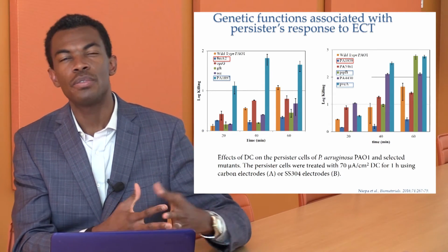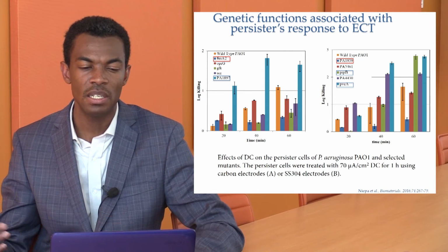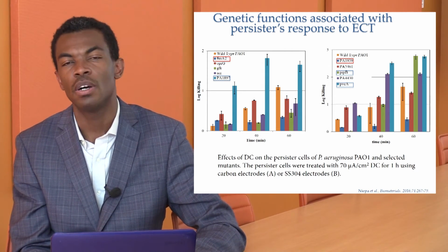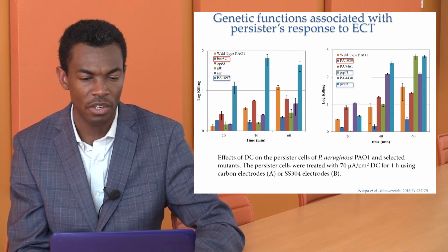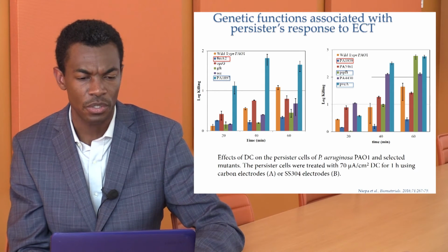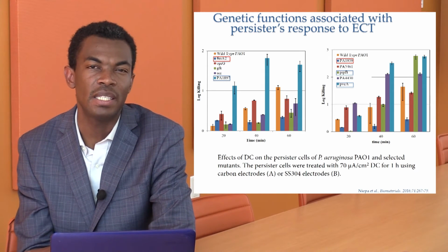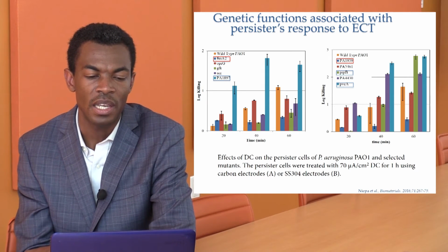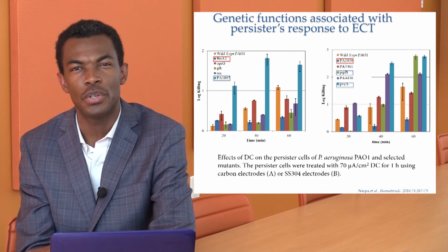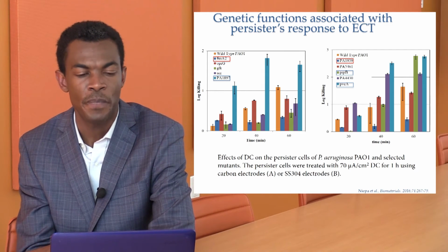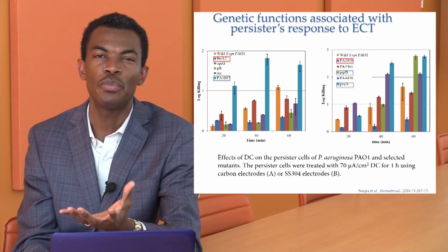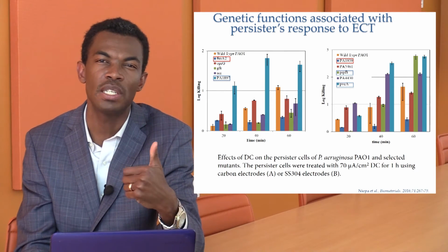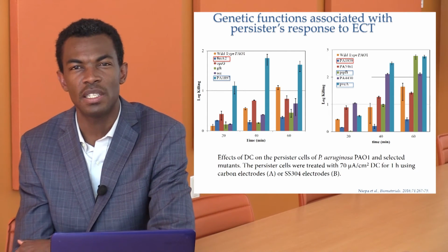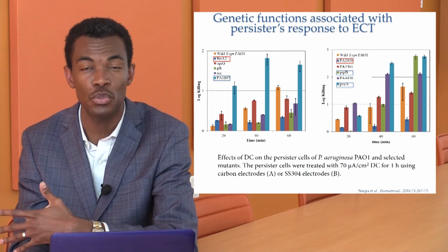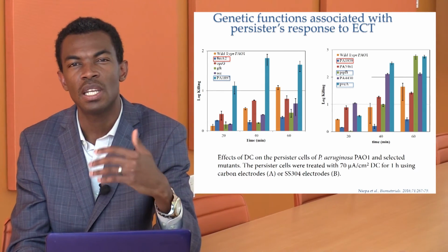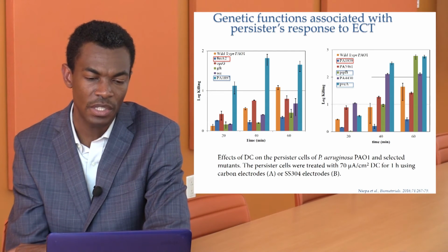Focusing on the genes that are involved in the treatment with carbon electrode versus the treatment with stainless steel, we performed the DC treatment to see how the deletion of those genes affects the viability of the cells, and we found some very interesting responses. The mutant of PA1897 that we just referred to gets very much killed by the electrochemical current generated by the carbon electrode when we only focus on this particular mutant. So not only does the mutant have a very low level of persistent cells, but performing the DC treatment using carbon electrode on this specific mutant leads to a high yield of killing, of cell death.